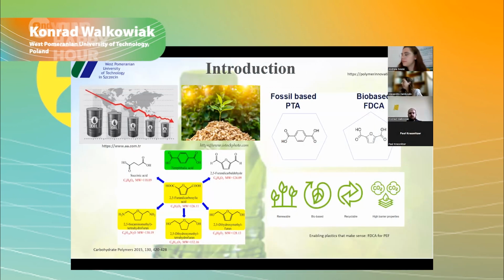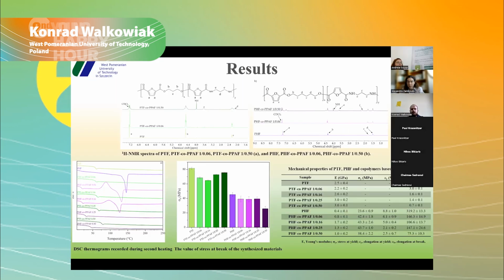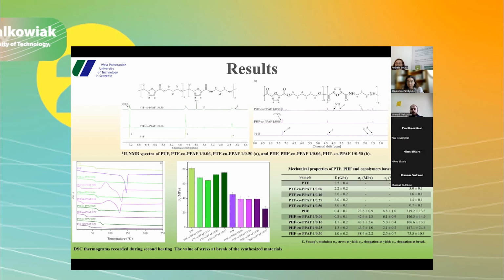Diminishing petrochemical resources, economic, political, and above all, ecological factors are causing growing interest in the industrial applicability of naturally impure raw materials such as polysaccharides, proteins, and fats. The interest in plant biomass as a raw material is due to its availability, chemical nature, and renewability. Unlike PTF and its copolymers, PHF and the series of PHF-based copolymers exhibited a yield point. The PHF and PHF series of copolymers had a higher value of elongation at break than PTF and copolymers based on it. This was due to the higher mobility of the molecular chains caused by a greater number of methylene groups.